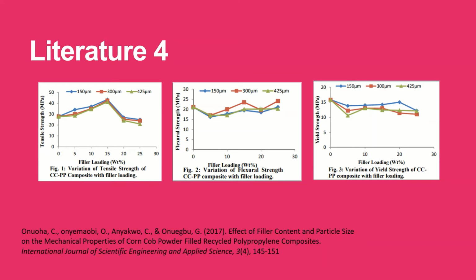Another relevant study was conducted by Onuoha et al. 2017, where the group investigated the effect of recycled polypropylene composites loaded with corn cob powder on its mechanical properties. The findings in Figure 1 revealed that the tensile strength of the composites was found to be higher than that of the unmodified sample. However, excessive incorporation of filler may lead to filler agglomeration in the polymer matrix, leading to formation of microvoids due to the difficulties in achieving a homogeneous dispersion of fillers.